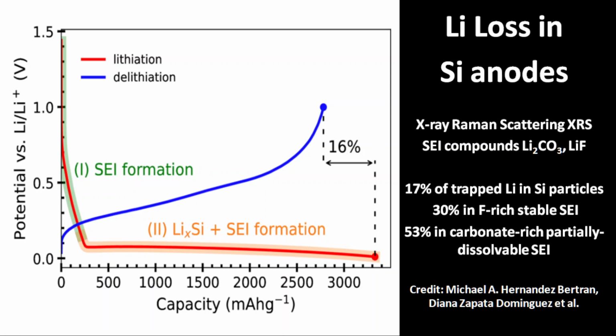This picture shows the electrochemical cycle in a coin cell. During the first charge-discharge cycle, there is an irreversible lithium loss in silicon anodes. It can be measured with synchrotron X-ray Raman scattering XRS. Main solid electrolyte interface layer compounds are lithium carbonate and lithium fluoride.